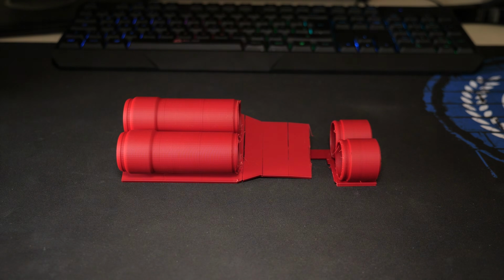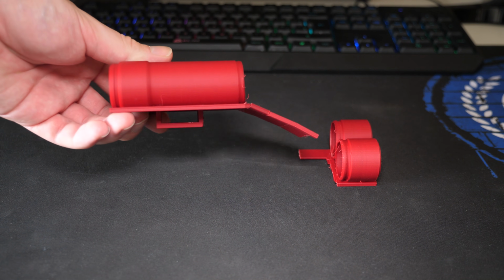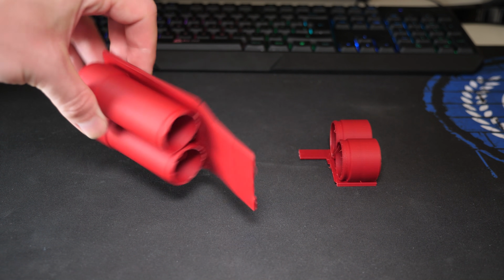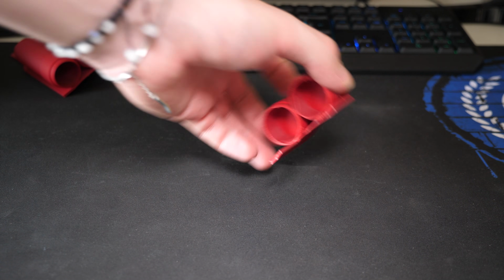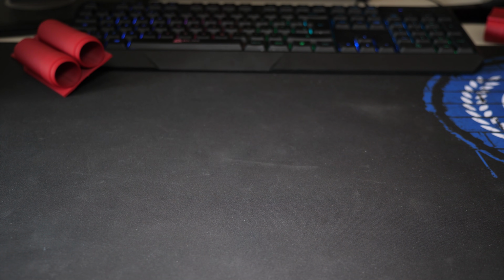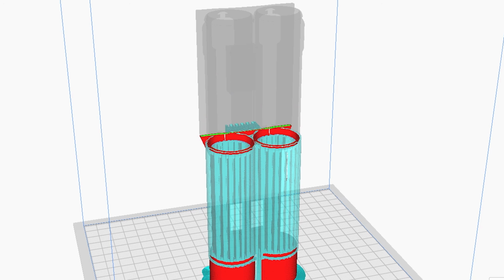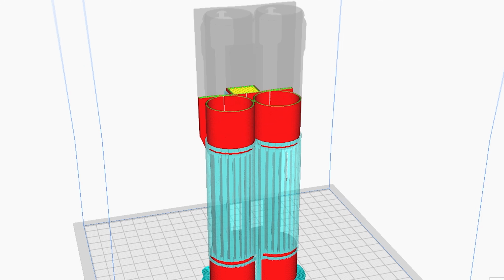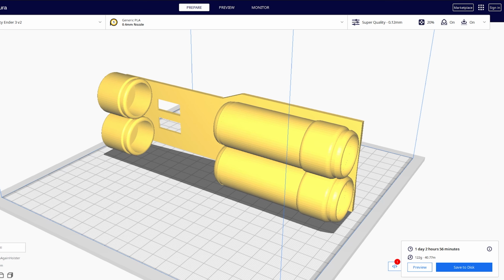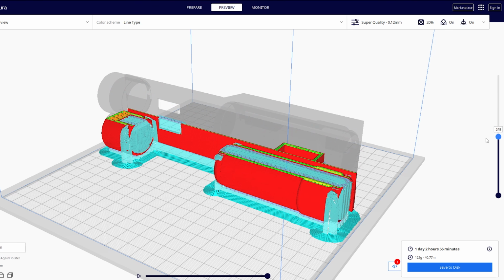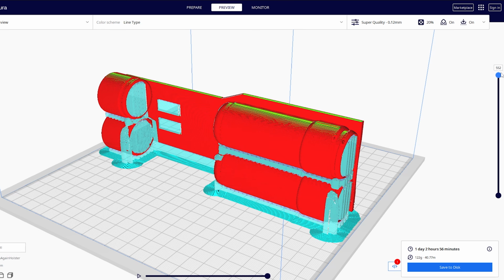While removing the supports, the thinnest part along the middle snapped in half several times. This happened because of how the layer lines ran horizontally across, making the holster fragile when bent along the grain. To fix the problem, I flipped the holster on its side, which changed the direction of the layer lines and would make the holster stronger. I hoped.